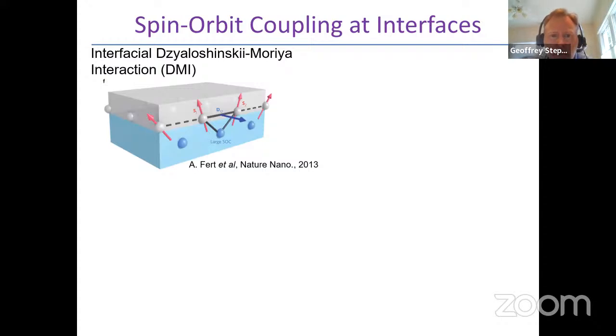But it was discovered some number of years ago that at a variety of interfaces, both in single crystal or polycrystalline materials, the presence of an interface between a ferromagnet and a heavy metal, so something like iron or cobalt or nickel, interface with something like platinum or tantalum, can give rise to an interfacial Dzyaloshinskii-Moriya interaction that can be quite strong and that can be quite robust against defects at the interface.